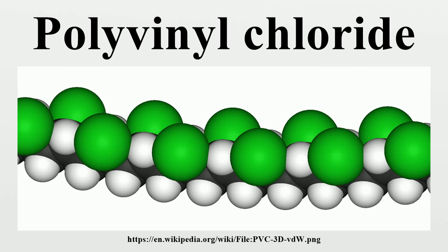Liquid mixed metal stabilizer systems are primarily based on barium, zinc and calcium carboxylates. In general, liquid mixed metals like BaZn, CaZn require the addition of co-stabilizers, antioxidants and organophosphites to provide optimum performance. BaZn stabilizers have successfully replaced cadmium-based stabilizers in Europe in many PVC semi-rigid and flexible applications according to the European producers.